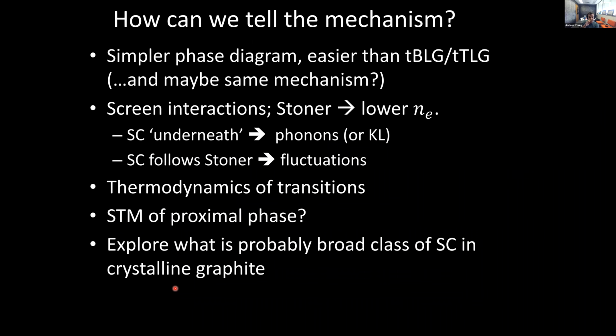I think we can tell there's some different things. The one opportunity is the fact that the phase diagram here, even though it seems kind of complicated when you try to talk about it all in one talk, is much simpler than, for example, in the moire systems. And by the way, you're basically taking graphene, you're using interlayer coupling to generate a large density of states, and then all hell breaks loose, including superconductivity. Probably the mechanisms are closely related to those moire systems, even though symmetries are different and there are a variety of other aspects that may not be the same, but presumably the underlying mechanism is related.